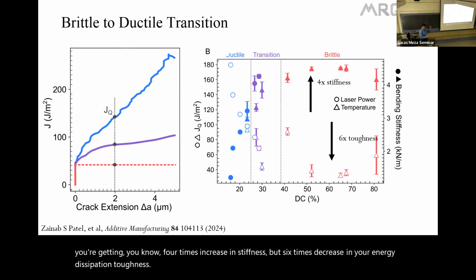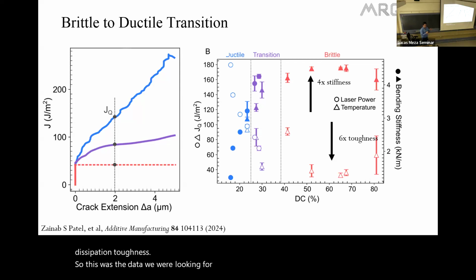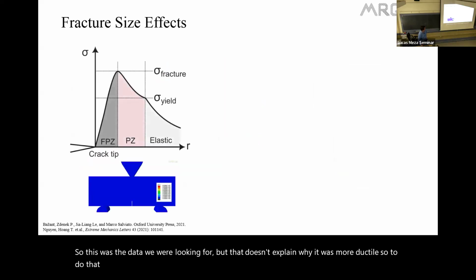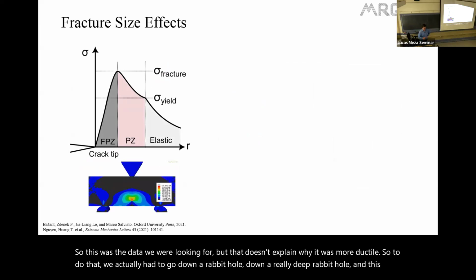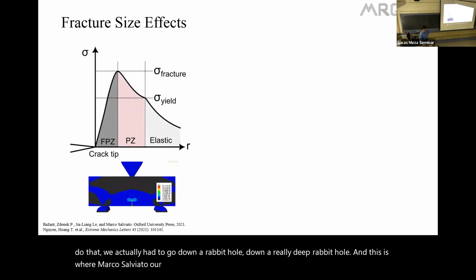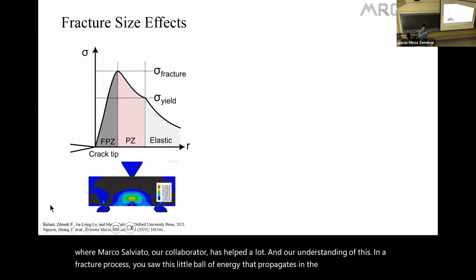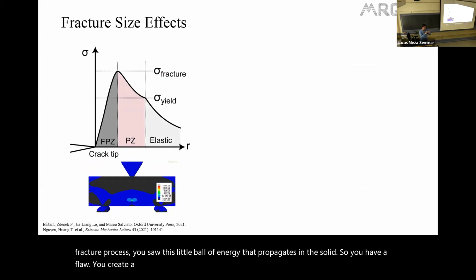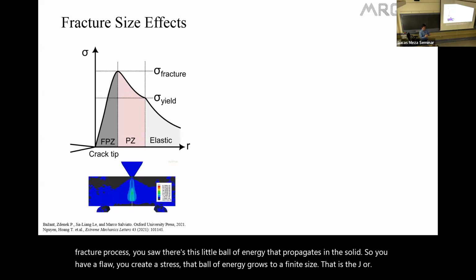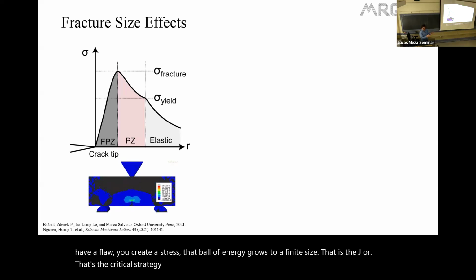So this was the data we were looking for, but that doesn't explain why it was more ductile. So to do that, we actually had to go down a rabbit hole, a really deep rabbit hole. And this is where Marco Salviato, our collaborator, has helped a lot in our understanding of this. In a fracture process, you saw there's this little ball of energy that propagates in the solid. So you have a flaw, you create a stress, that ball of energy grows to a finite size. That is the J or the G, that's the critical strain energy release, and then that propagates unstably through the